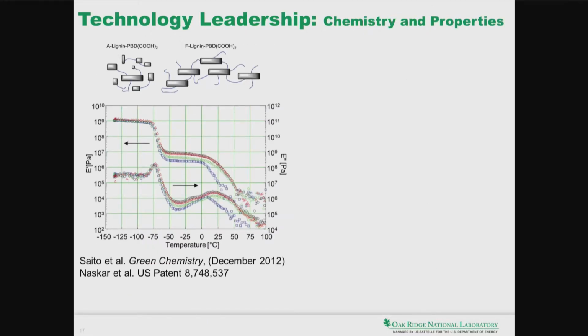Now, let us go back to our previous studies and why we are doing this. First of all, we did some preliminary work and we published and filed patents related to utilization of tailored lignin. We first did lignin modification by cross-linking to control the molecular weight and also the lignin glass transition temperature. Then we coupled it with different soft segments, telechelic polybutadiene, for example, in this case. You can see with increase in lignin content, here, of course, our lignin content was low, only 37%, the block copolymeric product flows near 25 degrees Celsius. So it proved the concept, but it was not a great product.